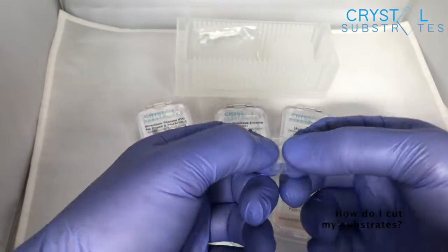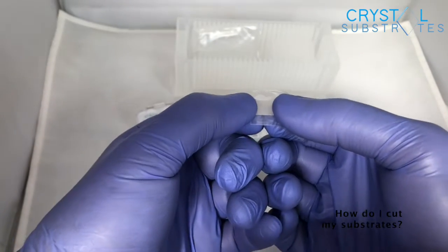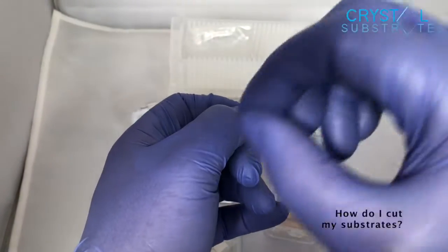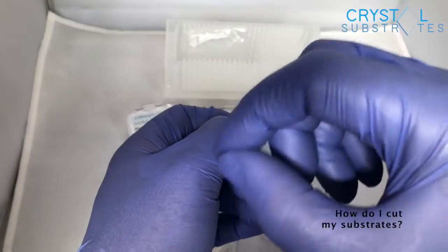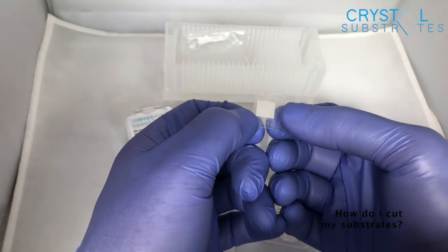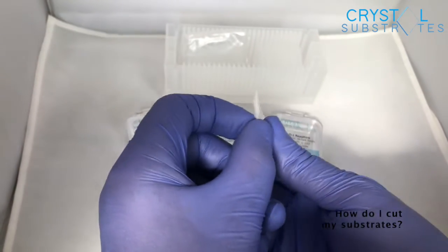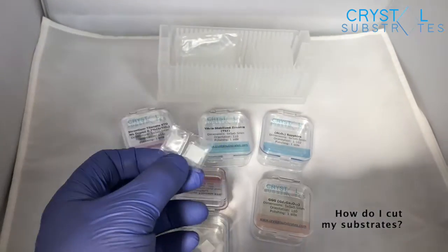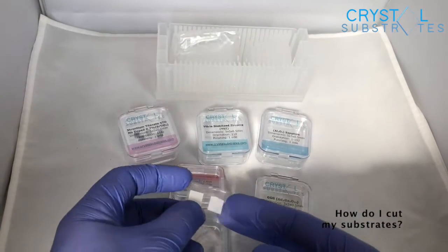If it's too light and you have to use too much force, it's not going to break cleanly. And if you're too hard, you might even break it while you're doing the scribing. So the thicker these get, this is a 0.5 millimeter thickness. When you go to about 1 millimeter thickness, they become quite a lot harder to cleave.